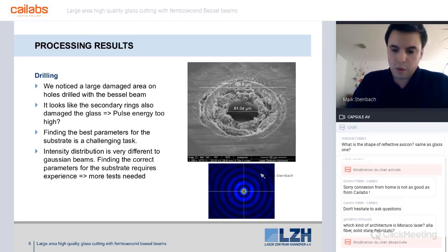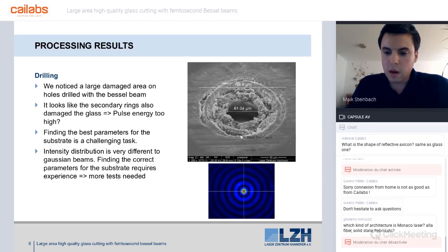We also tried to drill some holes with the Bessel beam. When we had a look at the SEM picture that you can see here, we would see a large damaged area next to the drilled hole. And if you compare that with the picture below, you could argue that the secondary rings of the Bessel beam also damaged the material. Probably the chosen pulse energy was too high.